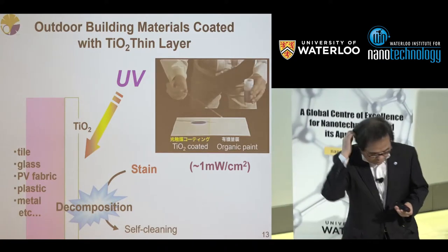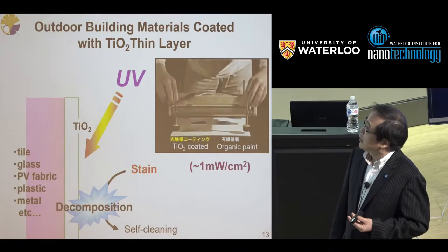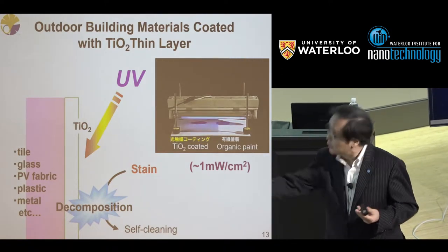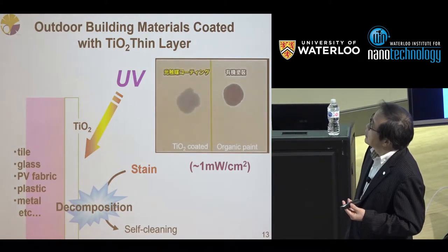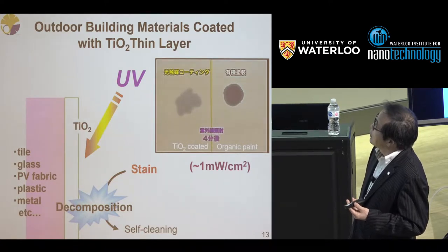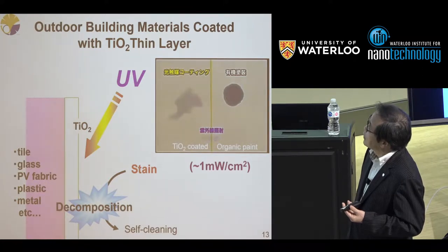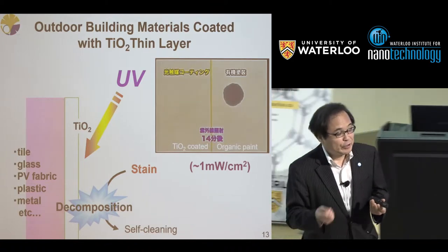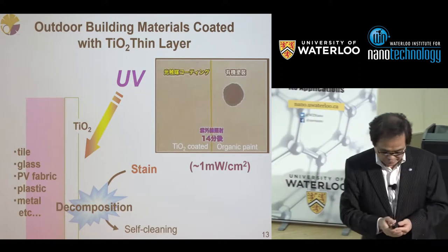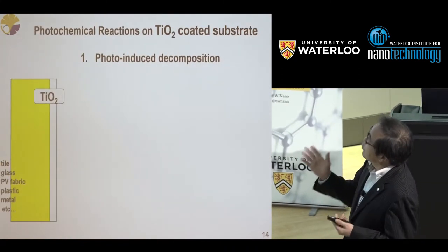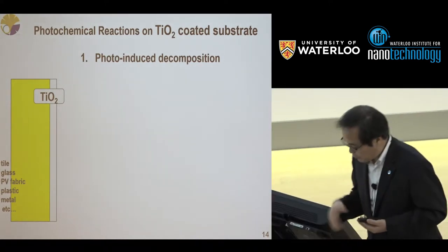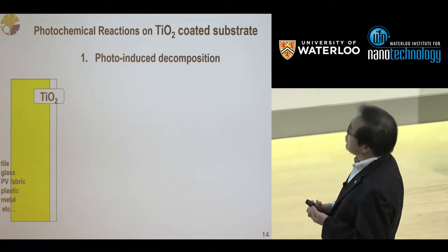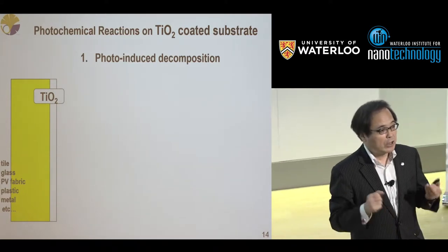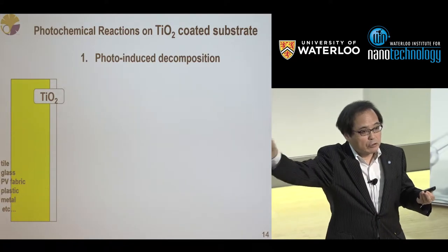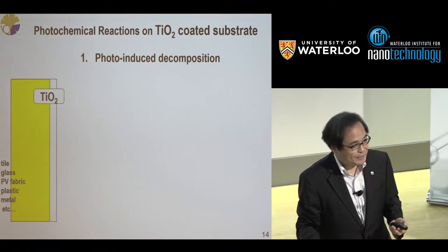So this is a blue colored organic compound, illuminated with 1 milliwatt, so exposed outdoors. Then this is 2 minutes after, 4 minutes, 6 minutes, 8 minutes, 10, 12, 14 minutes, okay, it disappears, like that. So if we expose this outdoors, that will be decomposed. Okay, that can be used. So when we coat various substrates with such a transparent photoactive titanium dioxide and expose them outdoors, such photo-induced decomposition occurs even without an additional artificial light source. Only the usual outdoor condition is enough, when the sun is shining.